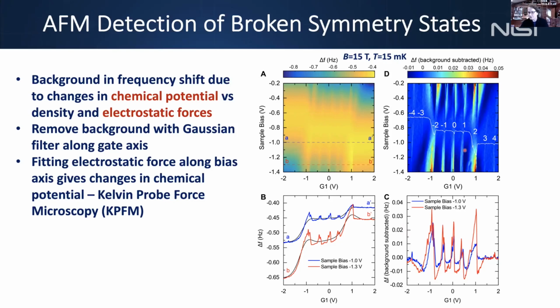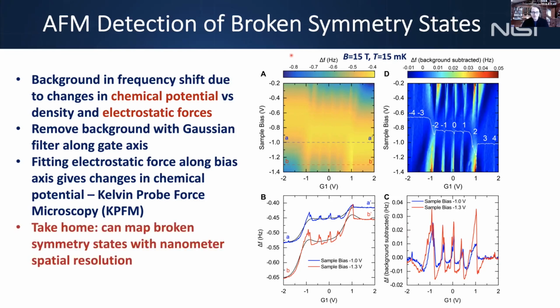And you can see all the integer filling factors, both in the 0 Landau level and plus or minus 1 Landau level, can be resolved. And this is done now at 15 Tesla and 15 millikelvin. So the great thing about this is that we now have a nanometer scale probe of broken symmetry states, which we can use to map out edge states or do whatever we want. The other benefit of this measurement is that you get the chemical potential here. So we can measure all the energies of the Landau levels.